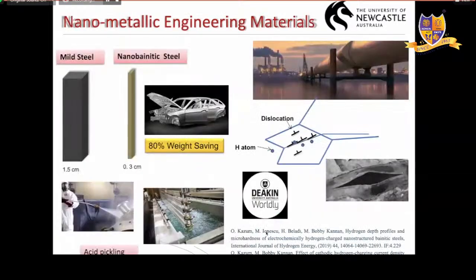And not only on biomaterials, we also work on engineering materials. We work on this fascinating material, nanobainitic steel, that has a very high strength. Just to give you an idea, if a mild steel requirement is 1.5 for a particular load, the thickness can be reduced to 0.3 if you use a nanobainitic steel, meaning that you have a lot of weight saving. Say, for example, you have a car, you replace the mild steel by nanobainitic steel, you have a weight saving of 80%.